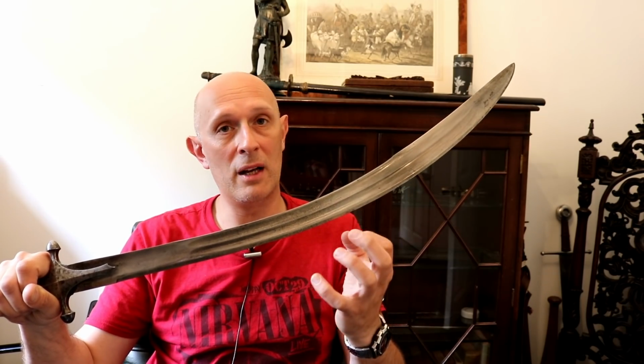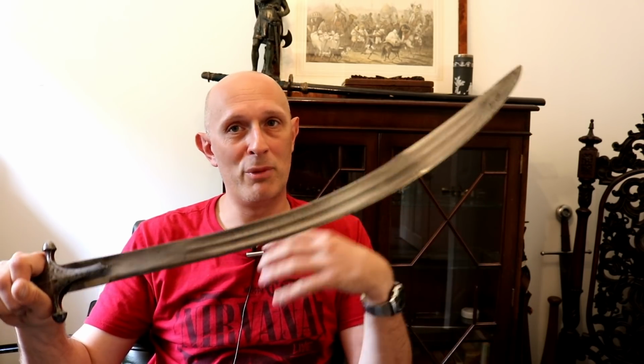I myself, on camera, have done restoration on a Wootz blade, and that Wootz blade, indeed, you can see is a different colour at the front to the back. That's not because of the material: we know it's Wootz, so it's crucible steel, one homogeneous piece of steel. But we know that therefore that must come from the heat treatment.